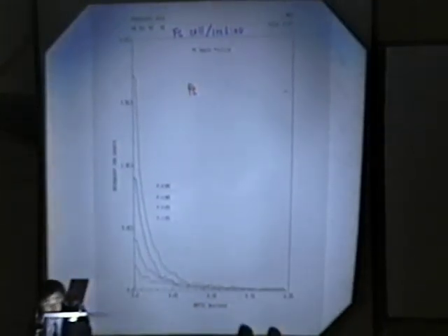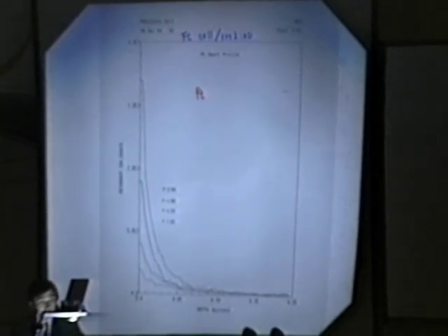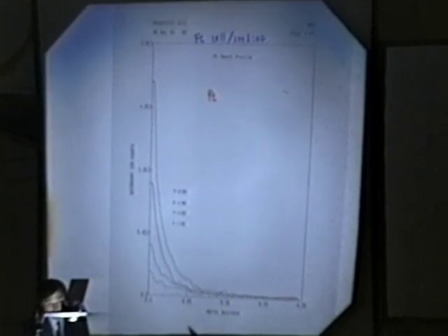This is predicted because in open cell systems the platinum anode dissolves and then gets deposited on the surface. And if we do SIMS analysis to get the depth profile, we have this very clear distribution along the distance from the surface to the bulk in the range of 0.1 micron. So platinum is very much concentrated in the surface region and then goes down very sharply towards the bulk.